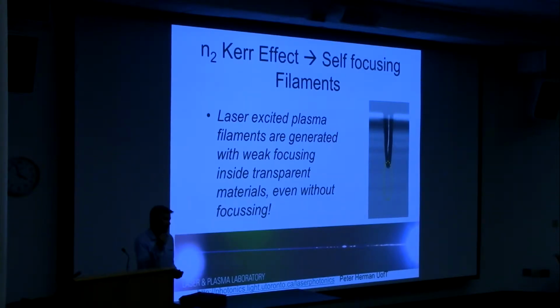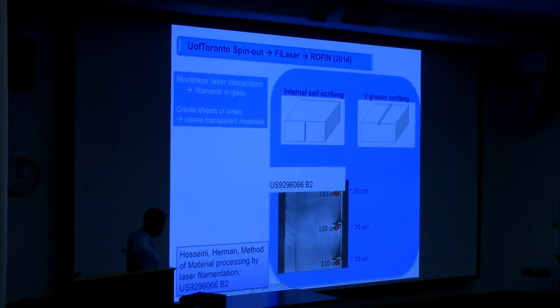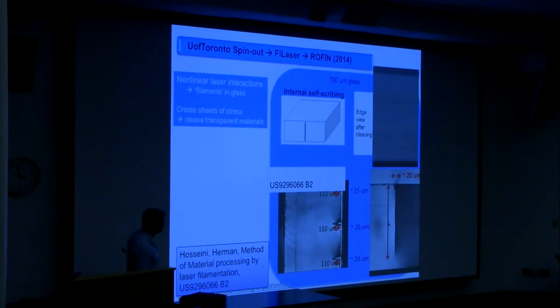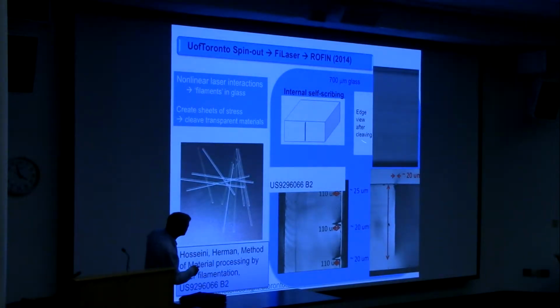But diamond saws has a lot of damage. It has a kerf width that's wider than this process. And so now there's these $1 million laser machines making filaments in all sorts of transparent materials, separating them. And it's really fun to see something discovered in a lab and then translated over some hard work into real processes. So there's our patent and just some pictures of that early work. And I'm not going to say much more, just that was a fun digression and led to something very important. So it turns out after cleaving, the surfaces under high magnification show the filament tracks, but this is much higher quality than generally diamond saws can do, and faster and lower cost.